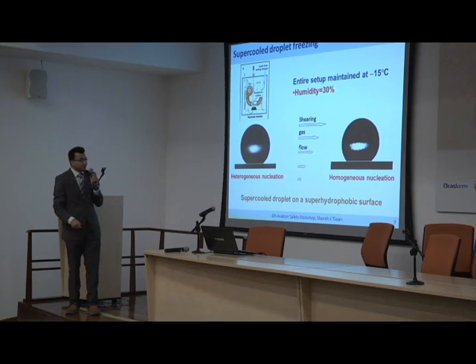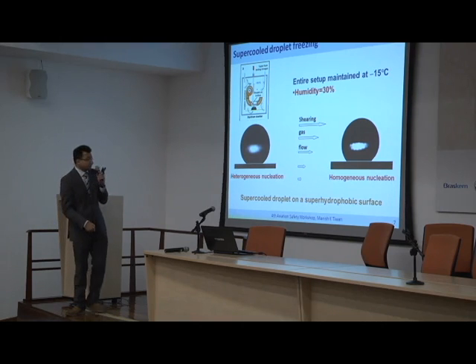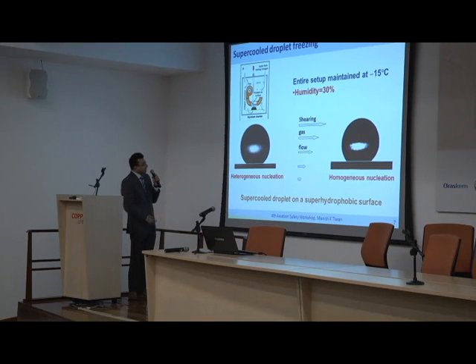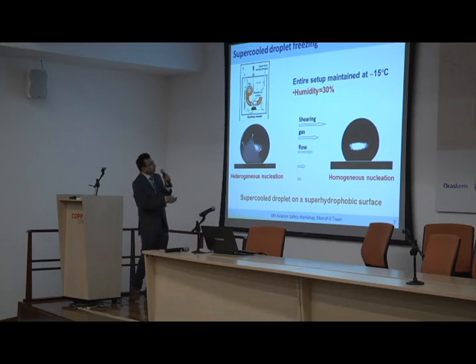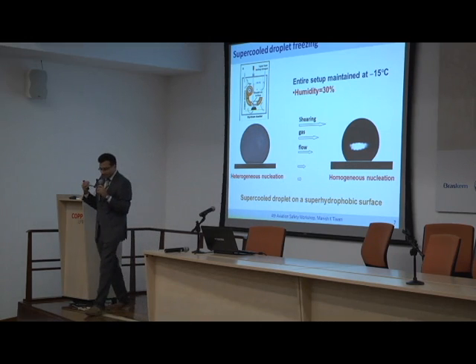And this is literally the outcome of the first 10 experiments that the student who graduated actually performed. So this is what he started observing. Here's a video. This is a droplet sitting on a superhydrophobic surface. And if we wait long enough, all of this is at minus 15 degrees centigrade in relatively dry humidity condition, what we see is we have nucleation down here at the interface between the droplet and the substrate. So this is heterogeneous nucleation. And this is not surprising.